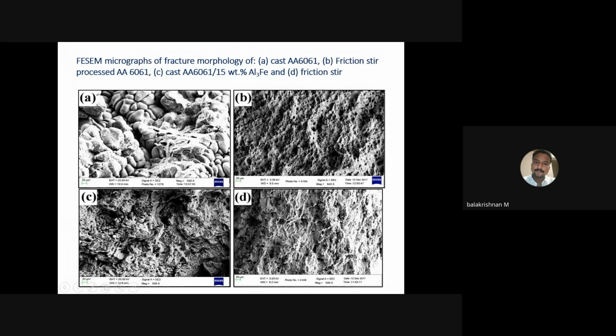Then fracture morphology of cast composite. This one is for the matrix, and this one is after friction stir processing. Then cast 15% of Al3Fe and friction stir processed. The cast matrix, so it is...